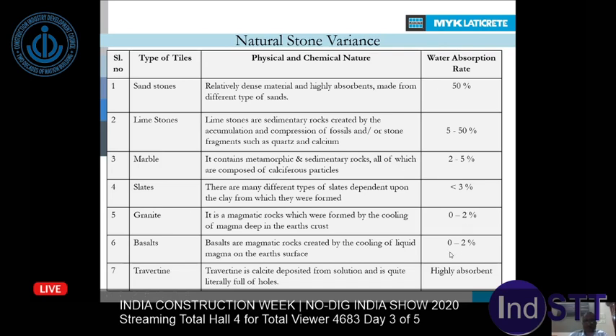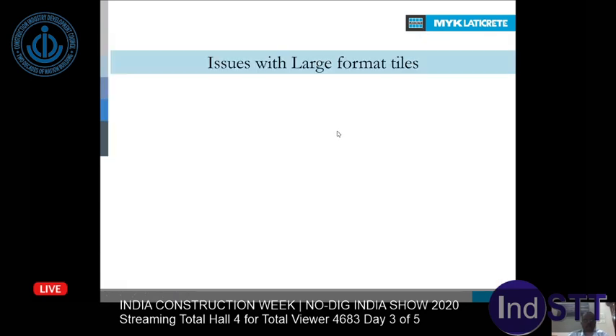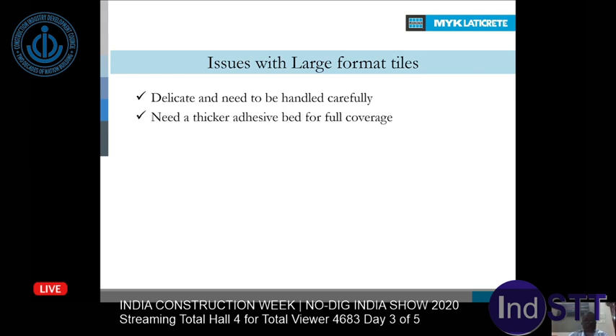Why is this important? Because this is really critical when we are selecting the right tile fixing materials, because the bonding and durability is highly dependent on the porosity of the stone or tiles. And also, as I said, nowadays we no longer see the small format tiles. We go with very large format tiles. They are very delicate. They have to be handled carefully. And since they are all large format, to cover a proper uniform bed thickness, you need a thicker adhesive bed.